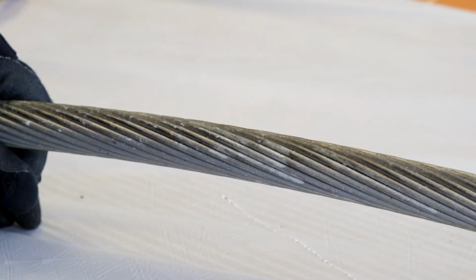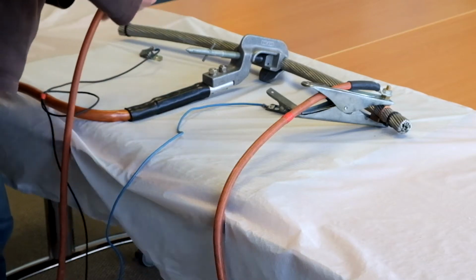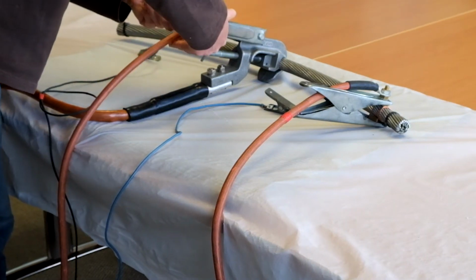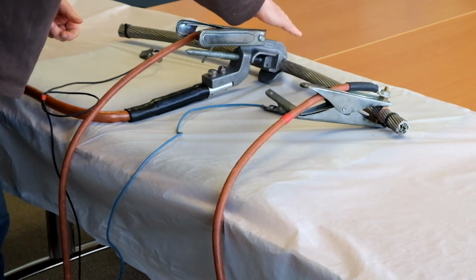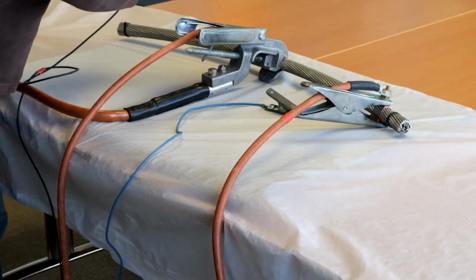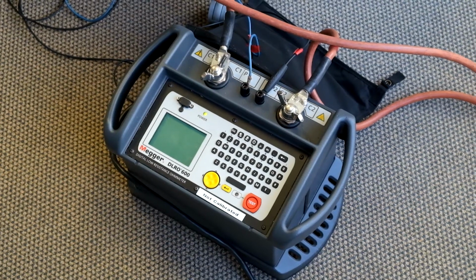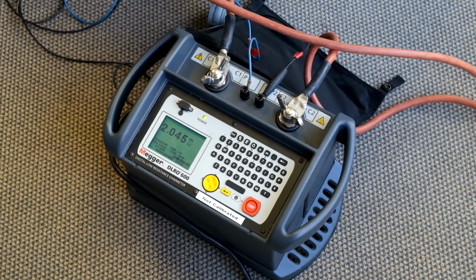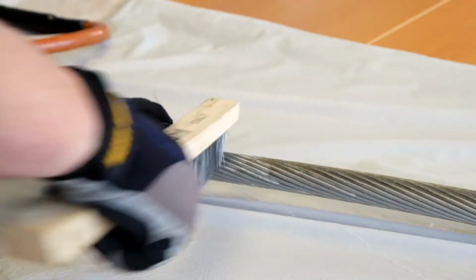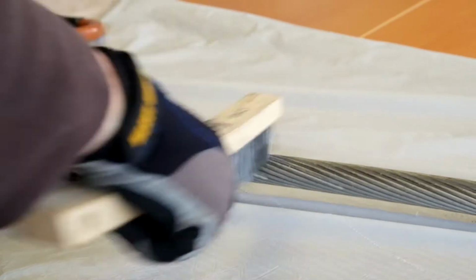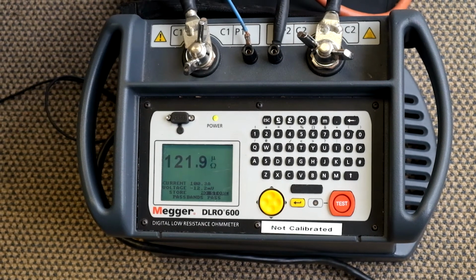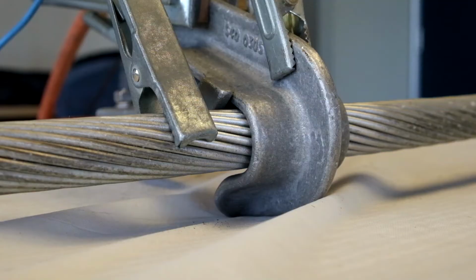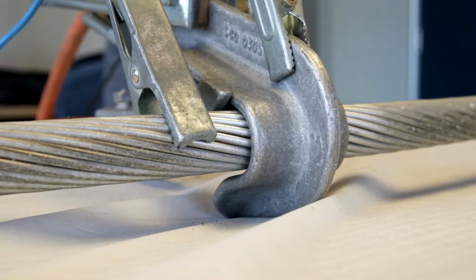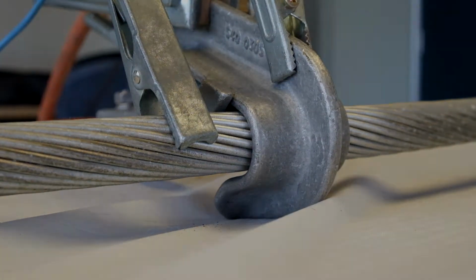The first sample is a piece of aluminium conductor, which has seen about 40 years of service life in the Wellington area. The conductor looks to be in pretty good condition. Before cleaning, the result is 2045 microohms. After a very quick clean, the result is dramatically less, at 121.9 microohms. That's reduced to just 6% of the uncleaned value.